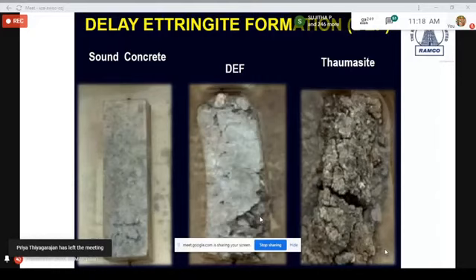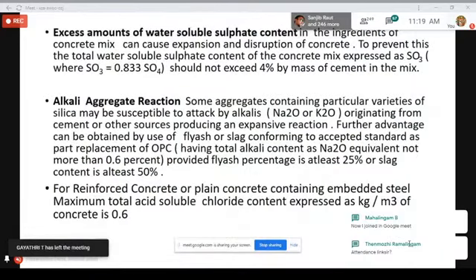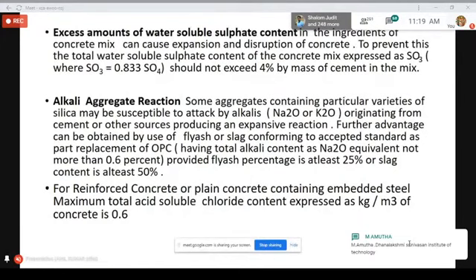Now, if you look at this, you might wonder from where I got these 3 points: the limitation of water soluble sulfate content, alkali aggregate reaction, and soluble chloride content. This is from our own Indian Standard codal provisions, which have given a lot of stress on durability of concrete. That is why you will find water soluble sulfate content, expressed as SO3, because SO4 is nothing but gypsum. The percentage of SO3 mentioned in the code should not exceed 4% by mass of cement in the mix. So the water soluble sulfate content is something which is limited.